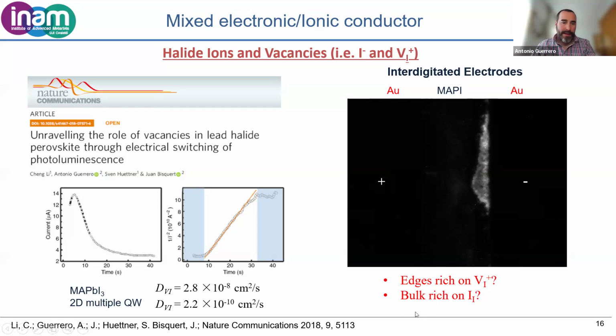So the PL gets quenched in these recombination centers. Okay, and by developing an electrical model and understanding how fast this dark front is advancing, we can, for example, calculate the diffusion coefficient of the vacancies, the halide, or in this case, it is believed that it is halide vacancies that are migrating inside the perovskite, and we get ionic diffusion coefficients very high, in the order of 10 to the minus 8, for perovskite containing methyl ammonium lead